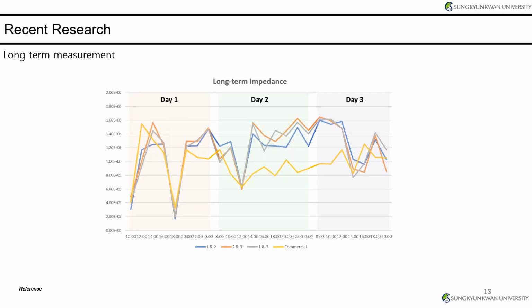And we conducted a long-term measurement test using the electrode with 60% dissolvent. We were able to continuously measure EP signals for 3 days during daily life activities and even exercise without destroying the electrode. So we demonstrate stable and reliable performance. Thank you for listening.